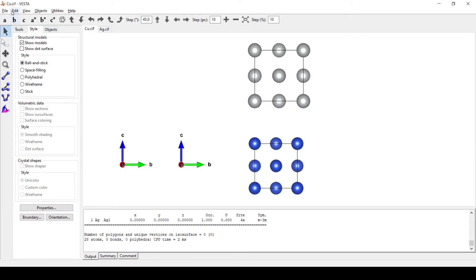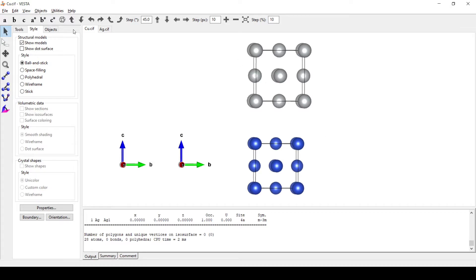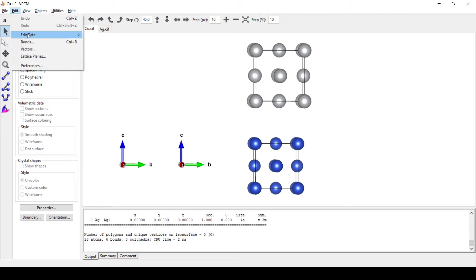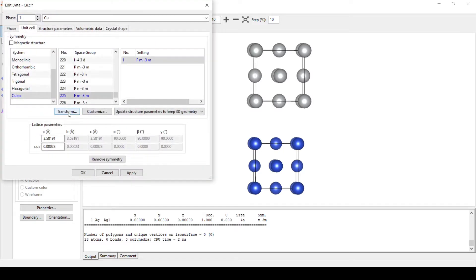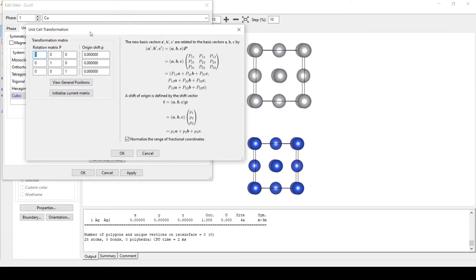Now as we know, there is a difference between both unit cells and this is not yet a heterostructure — these are unit cells placed one above another. For building a heterostructure we need a single unit cell with both structures one above another. For that we will expand this by multiplying with the integers. Go to Edit Data Unit Cell and here we will transform the matrix. For copper it would be 8 in both A and B dimensions without touching the C dimension.